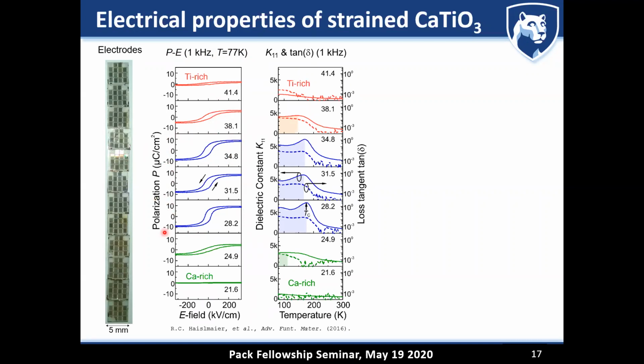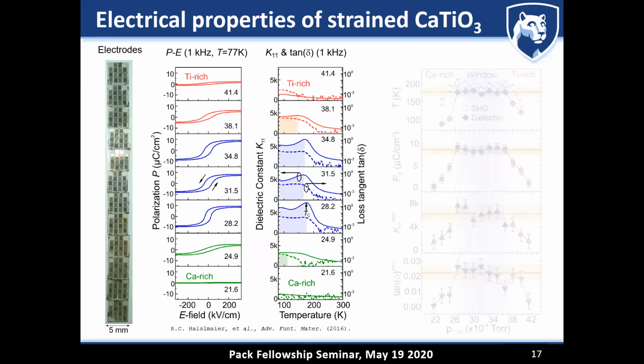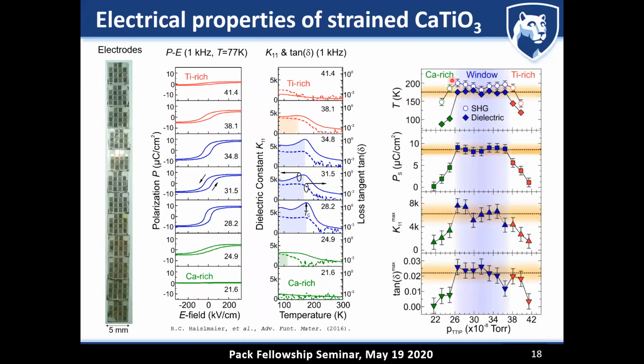We could also trace the transition temperature for the ferroelectric to paraelectric phase transition by looking into the temperature-dependent dielectric constant measurements. You can see here that there's a peak, an enhancement in the dielectric constant, typically an indication that there's a phase transition happening. And basically what we did, we tracked this ferroelectric to paraelectric transition temperature, and the signal that we've gotten from second harmonic generation as a function of growth condition.